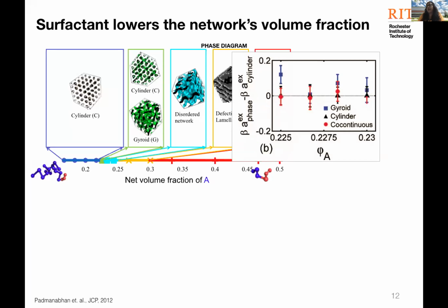That is something where, thermodynamically, your error bars are fairly big, so it's hard to tell if it's actually significant. But in a massive melt situation, you could have a phase separation similar to what you see in colloids when you have the FCC versus HCP lattice, where the free energy is an extremely tiny fraction of a kT per particle, but when you get to the system as a whole, it's so vastly preferable that that's the type of thing you see.